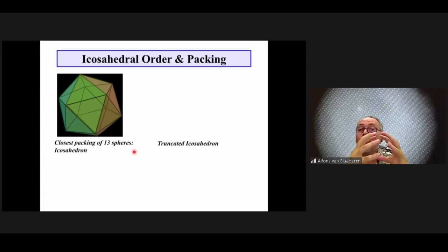You can get it locally somewhat more compact, and a way of locally measuring the volume fraction is, for instance, to shrink wrap it. That's a good way of defining a local volume. You can also, of course, call that the Voronoi volume and the convex hull of that packing. But that packing of an icosahedron is slightly better than that of a close-packed structure. But an icosahedron has five-fold symmetries, so we cannot continue that in 3D, and that is very important.